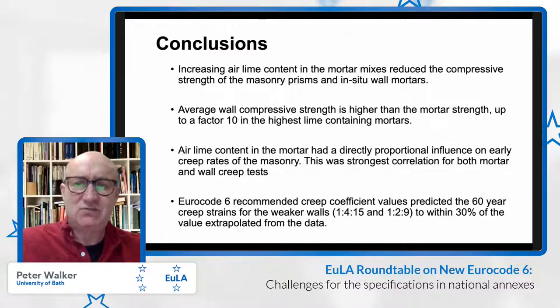relatively speaking, more important, and that is reflected in the current Eurocode 6 equation for calculating the characteristic flexural strength of masonry, as Meera reported on earlier. The air content in the mortar had a direct proportional influence on early creep rates, for both the mortar and the masonry, and was the strongest correlation. So air content, which directly relates to mortar strength, was the strongest correlation